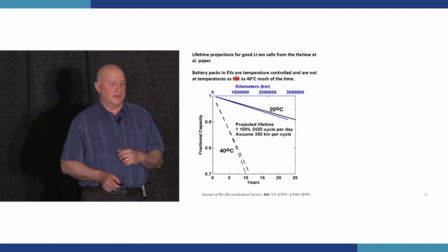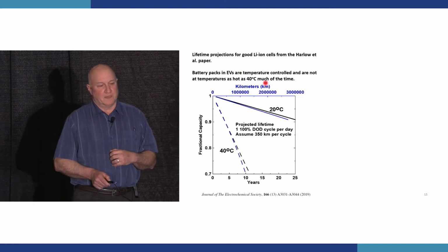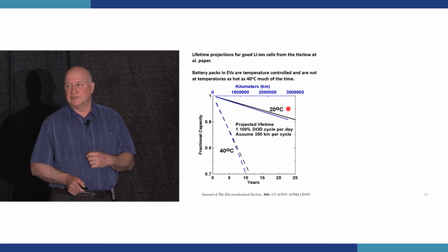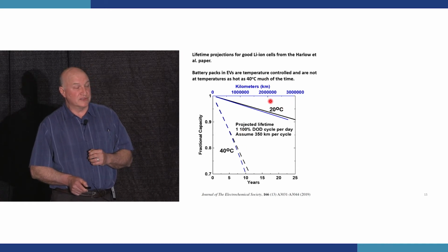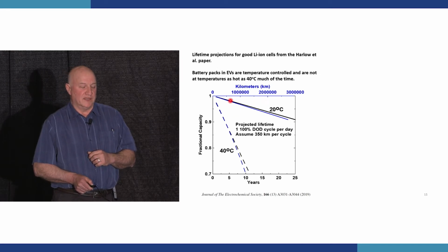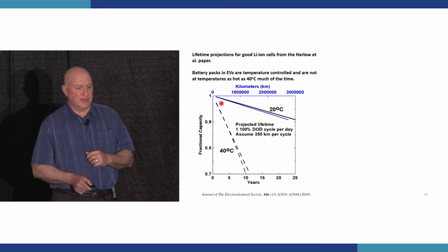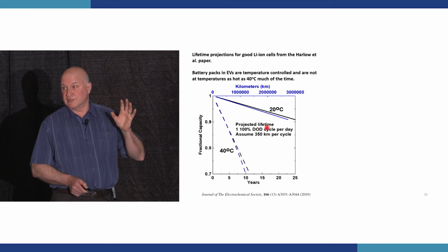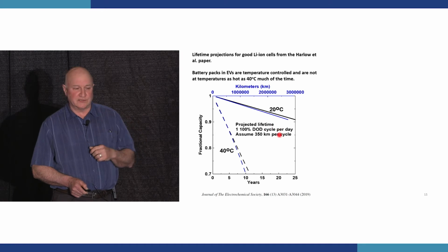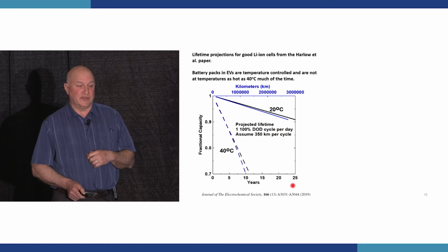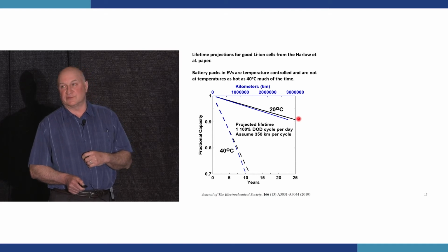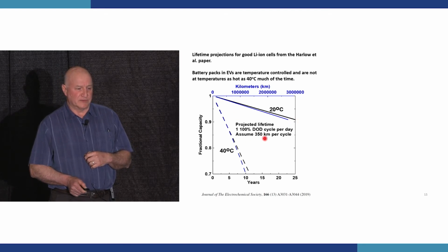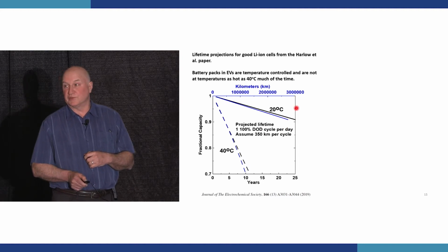So in that Harlow paper, we made projections for the lifetime of these cells at both 20 degrees C and 40 degrees C, and we did this by combining the results of charge-discharge cycling experiments with storage experiments. And at 20 degrees C, if you follow the black line, we're plotting the fractional capacity that the cell would have if it were undergoing just one charge-discharge cycle a day with a 3-hour discharge and a 3-hour charge. And after 25 years of testing, it would have about 90% of its capacity remaining. If it were used in a vehicle and there were 350 kilometers for every charge cycle every day, it would drive about 3 million kilometers in that 20-plus year period.